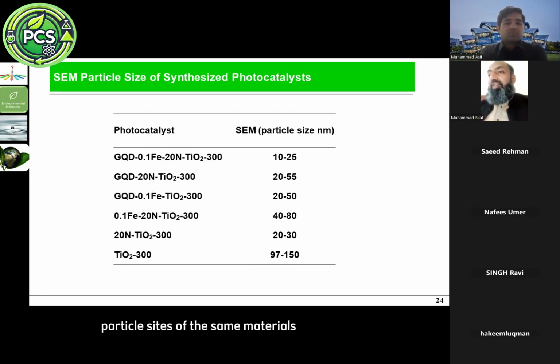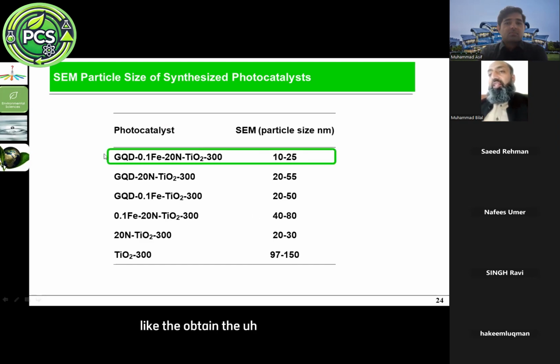And here are the particle sizes of the same materials through a scanning electron microscope. Here we obtained the particle size of the graphene quantum dot iron nitrogen titania when they were calcined at 300 degrees centigrade. We can observe that the titania, when calcined at 300 degrees, showed a particle size of 97 to 150 nanometer. And through different dopant ratios, finally we were able to achieve the finest material with a particle size of 10 to 25 nanometer.